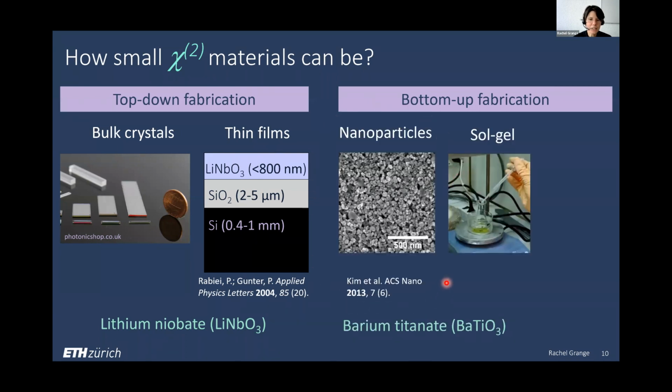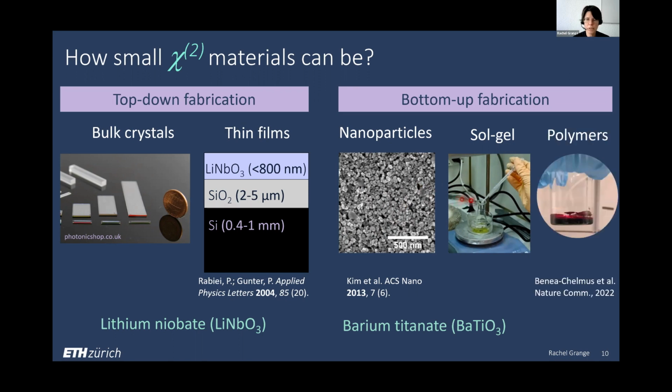And we started to be interested in working with nanoparticles that you can get by hydrothermal process or molten salt synthesis, how to nanoimprint them, as well as sol-gel, because there you really start with a smooth material, though both are polycrystalline. So you will not get a monocrystalline layer but a polycrystalline layer, but as I will show you, they are still powerful and show many of the properties that I was talking about before.